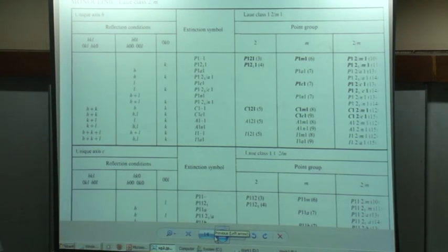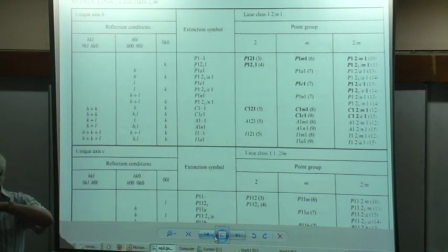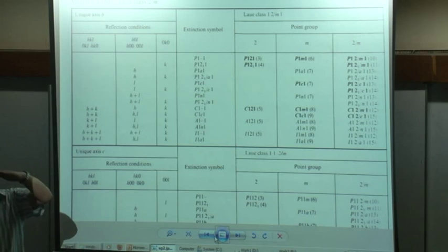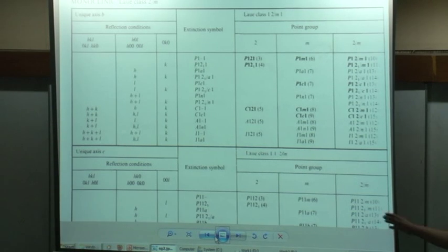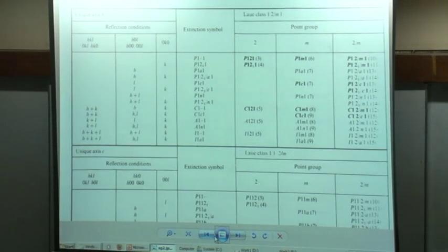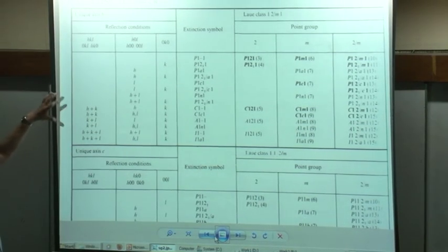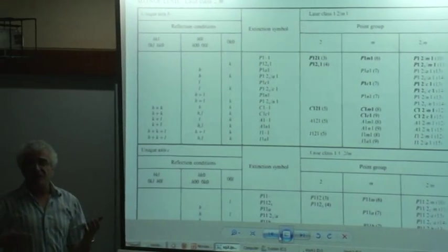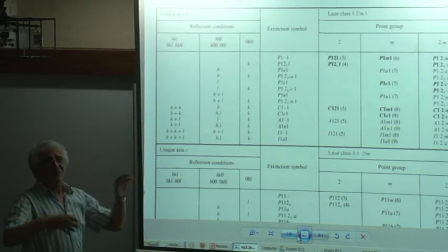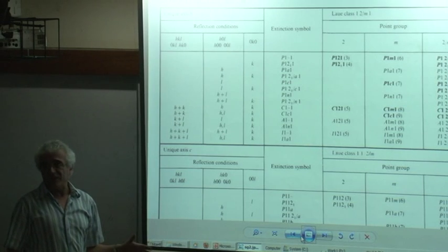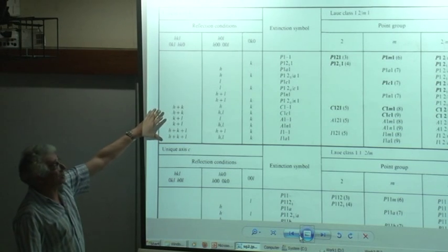These days, if you look at International Tables for Crystallography, which is like the Bible for us as crystallographers, it's a great big book like this, and it's got these determinative tables inside. This makes life a little bit easier for us. This gives you the types of things that you look for. For a monoclinic system, which is very common, particularly for organic crystals, let's say 70 to 80% of organic crystal structures are monoclinic, these are the most complicated things that people will usually deal with.